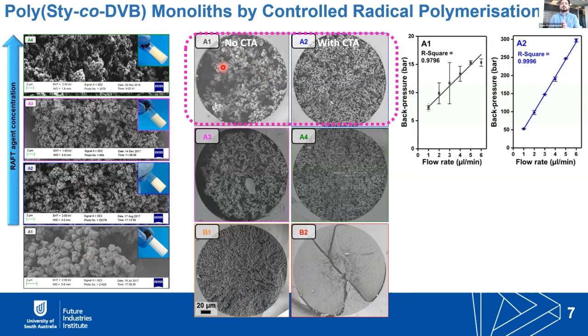And the nice thing here is that the back pressure, which shows the repeatability of these, can be obtained much, much better when we are using the CTA. This is 7 times repeat of the same recipe on different days. So this is a very interesting result.